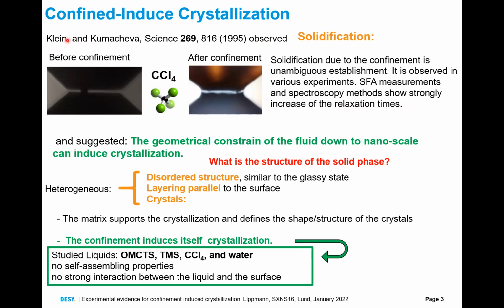So when Klein and Kumacheva observed this solidification, they suggested that the geometrical constraints can lead to crystallization. This started a lot of discussion in the community, which continues nowadays, about what the structure of the solid phase actually is. Nowadays we know very well that the structure in confinement is a mixture of disordered structure and also layering on the surface.